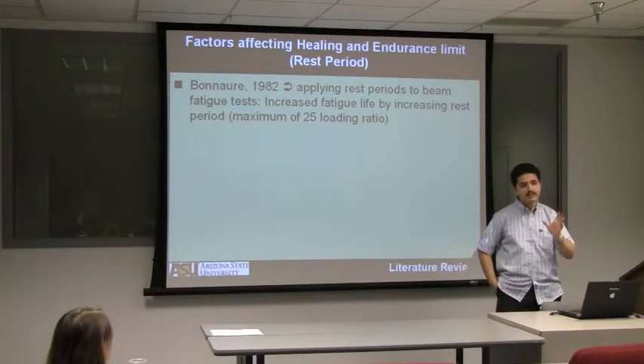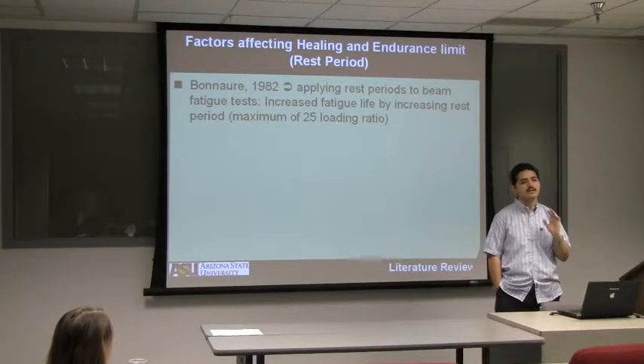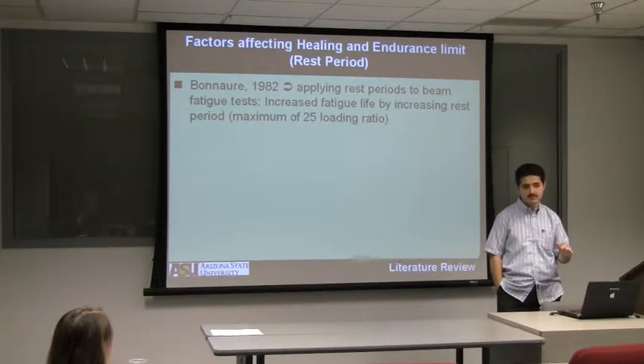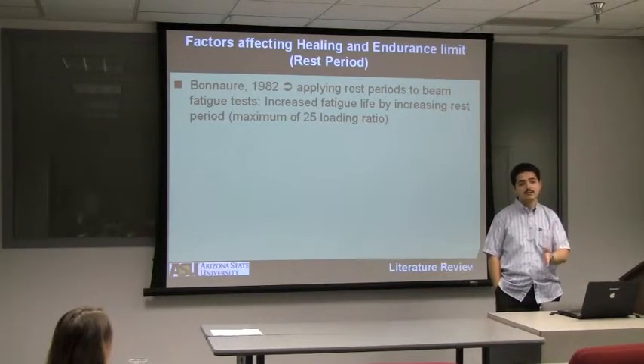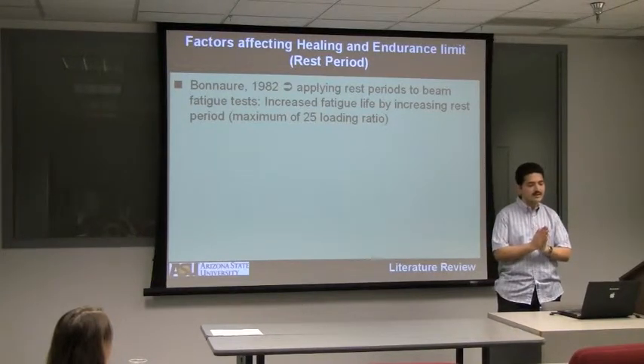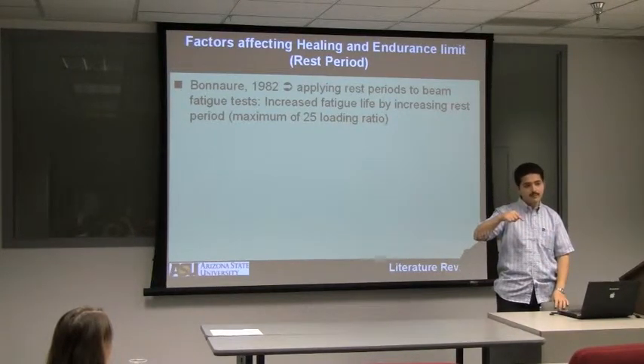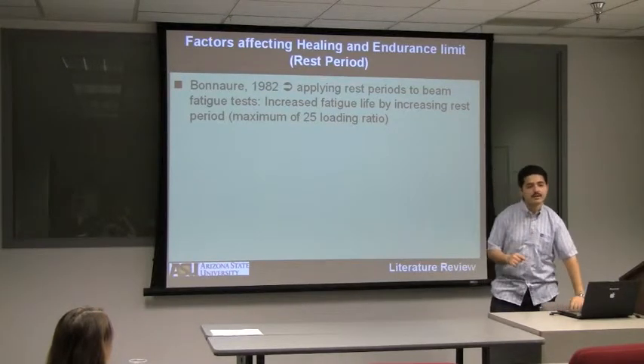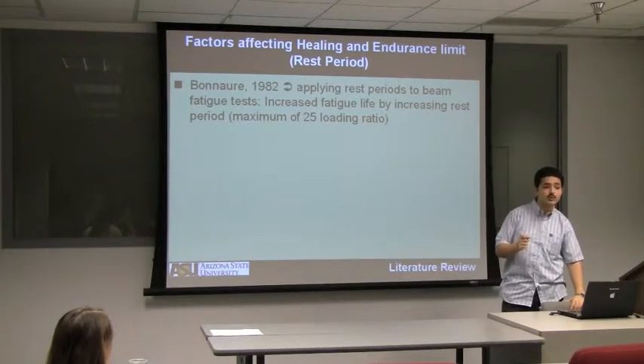But something interesting that he mentioned here is that you will get the maximum healing possible by applying a rest period equal to 25 times the loading time. Let me stop here and explain. For the loading time, I apply a loading time equal to 0.1 second. So that means I apply 10 cycles per second.